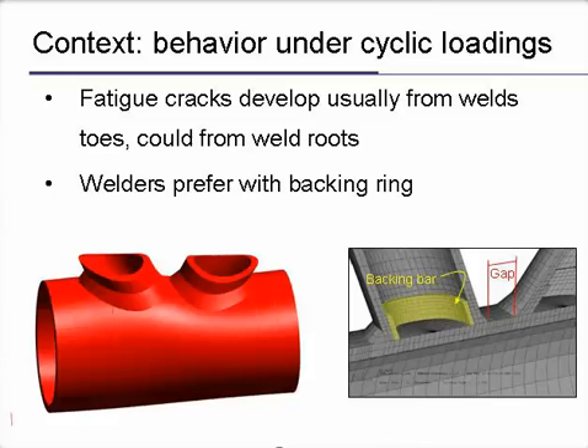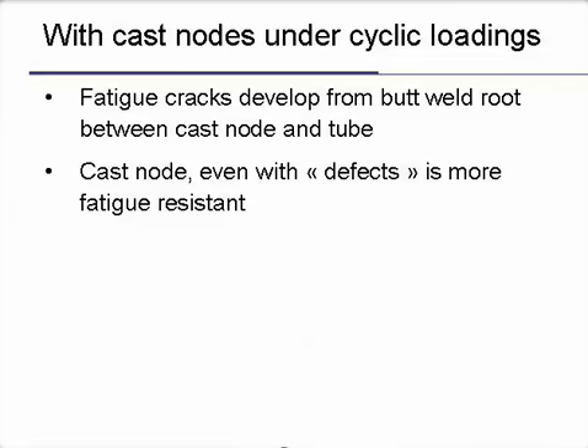In Switzerland, I don't know how it is here, but welders prefer these weldings with backing bars or backing rings. So generally, you don't have any problem of having cracks from the root. It's really coming out here in the middle or at some other point, but mainly what we have seen is always at this point in diagonal tension here that you get the cracks. But it's not always the case. There can be other geometries, and you can have effectively cracks from the root.